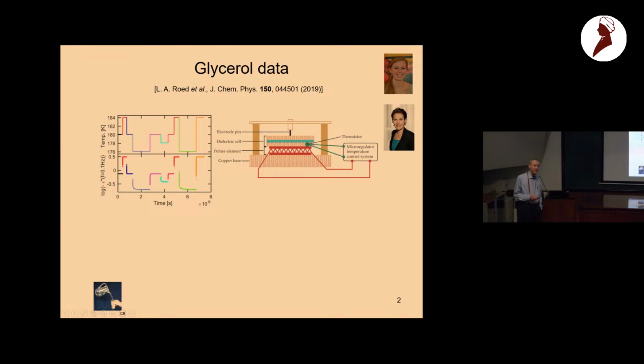In this case, it's a very low frequency dielectric loss for historical reasons. Nowadays, we usually measure at 100 kilohertz, the real part, but this is the imaginary part at much lower frequency. But it doesn't matter. We just measure something that we can measure accurately. And then basically you see that when you jump down here to 176, the measured signal eventually equilibrates. And this is what we want to understand. How is this process actually taking place?